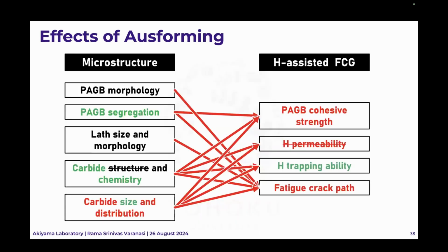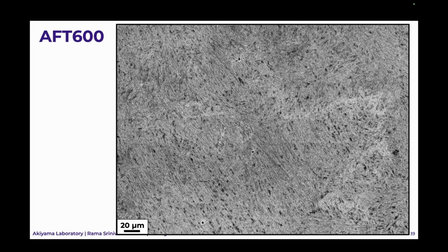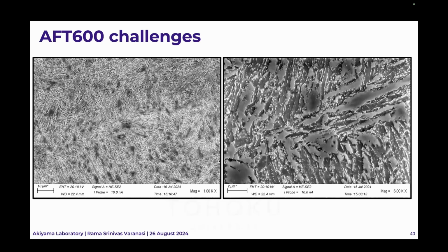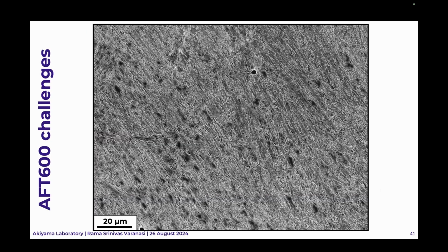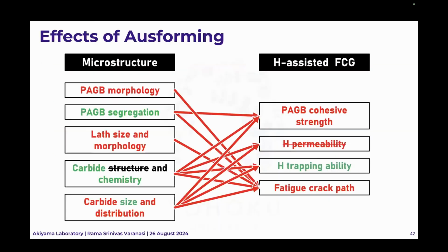Now, 2 minutes. Okay. So the other things, but we also have a few challenges. Firstly, in some areas, we find it very difficult to determine what exactly is the prior austenite grain boundary in the Ausformed material. And in some cases, we see these laths which are about 120 or 150 micrometers in length. The prior austenite grain size is not this big. This might happen probably because during Ausforming, we are causing only one variant to be selected. The prior austenite grain boundary segregation, we are yet to do based on APT studies.